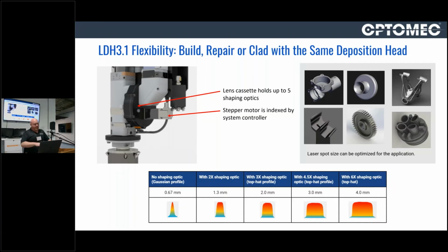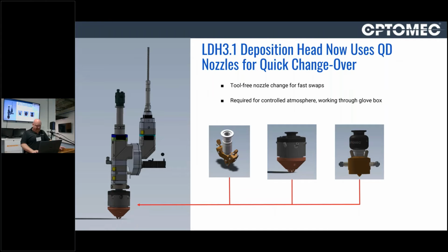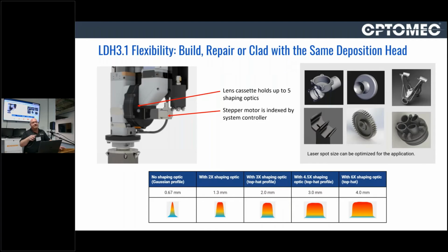That flatter power distribution is really key when you're doing high power deposits. Without it, you end up with a hot spot, say in the center, or typically off center, and you can vaporize material in that one spot while the rest of your melt pool looks beautiful. A nice flat profile allows you to have nice gentle deposits. Because that's controlled with a stepper motor, it can be CNC programmed. So within a tool path, I can call different configurations of spot sizes.